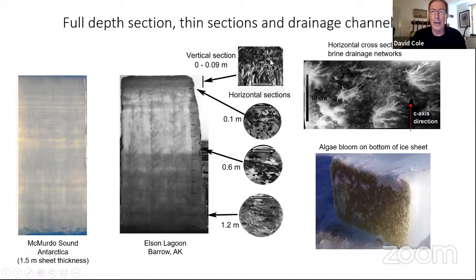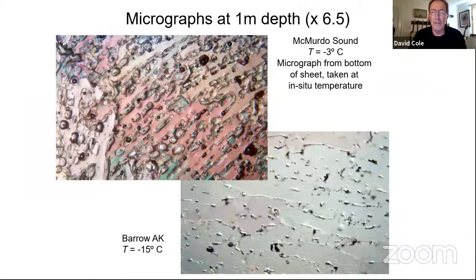Generally, there's a granular layer up near the top, maybe 10, 20, or sometimes more centimeters, that basically forms during initial freeze up. Once the congelation ice starts, you get this columnar growth, typically with increasing grain size with depth. When there's an under-ice current that's prevalent for most of the time, then we'll actually get an alignment of the C axes of the grains that are growing. And I'll talk a little bit more about that later on. So that's our material.